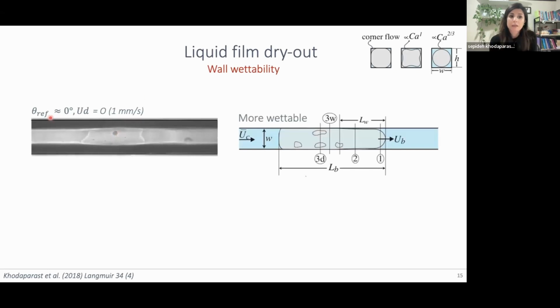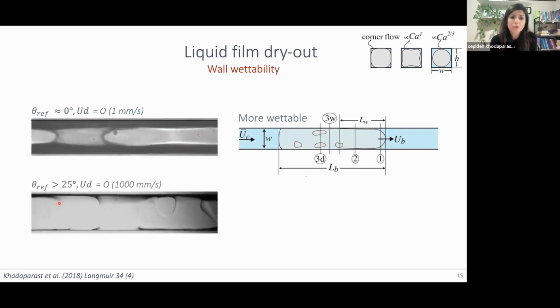But because the wall is quite wettable, the speed of the growth of this dry out front is not too fast. So you can track it, these are high-speed videos, but at least in the high-speed videos, you can see them moving. But when you go to channels which are less wettable, you see that the growth of this dry out patch is quite spontaneous, and it fills up the entire channel.